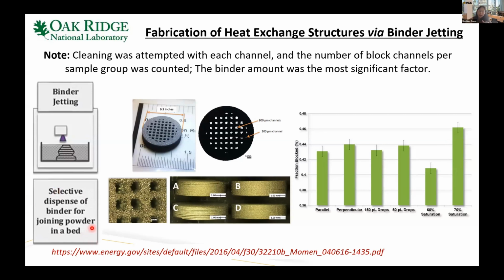So it joins the powder layer by layer. The Oak Ridge group has been able to make microchannels with channel widths as small as 800 microns. But the smaller they get, the more clogging was observed.